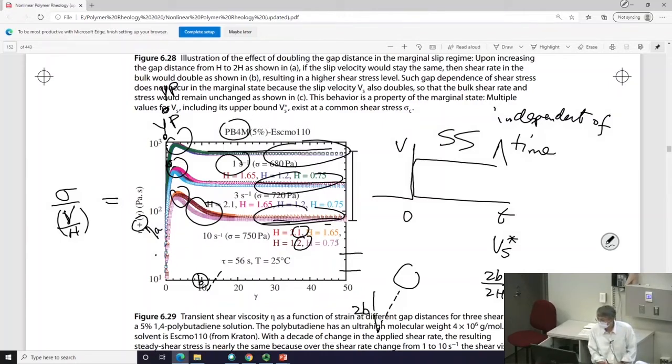Good point. So let me rephrase that logic. If there's no slip, then of course your result is sort of independent of the gap. I may even mention that in a parallel plate geometry, usually our H is half a millimeter to 1.5 millimeters in rheometry. When it's smaller than half a millimeter, maybe because of alignment, maybe because of some other reasons, we typically find some gap dependence, which I have never had enough resources for my student to investigate. I once did a calculation that if there's misalignment, not being vertical, your shaft could give you that. But to answer the question directly, if you are staying above half a millimeter, you are safe. And of course, you cannot be too big, right? Because then you become a cylinder. So yeah.